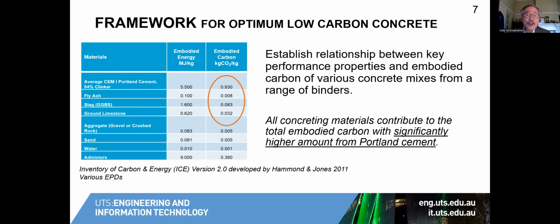Now, if we can replace some of it with slag, that has basically an order of magnitude lower embodied carbon than Portland cement, and that is 0.083, as you can see there. And if you also use fly ash, it's even another order lower than slag, at 0.008.